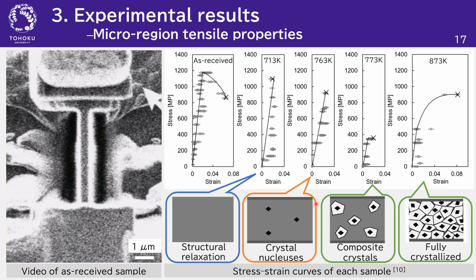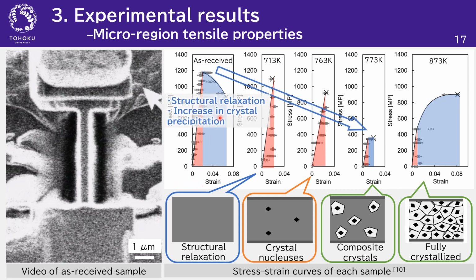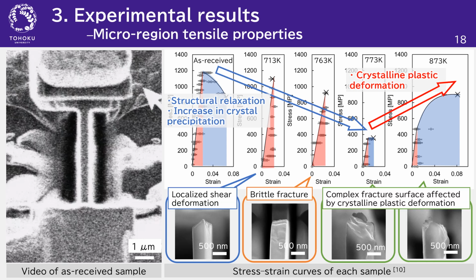These are the stress-strain diagrams for all samples. The vertical axis shows tensile strength and the area under the stress-strain curve shows toughness. Strength and toughness decrease with increasing structural relaxation and precipitated crystals. On the other hand, when fully crystallized, crystalline plastic deformation increased and the strength and toughness increased again. Furthermore, we observed the fracture surface of each specimen. Specimens exhibit a microstructure-dependent fracture shape.